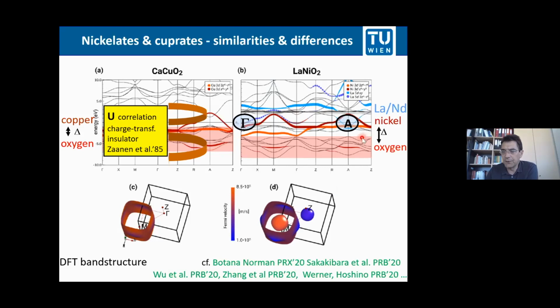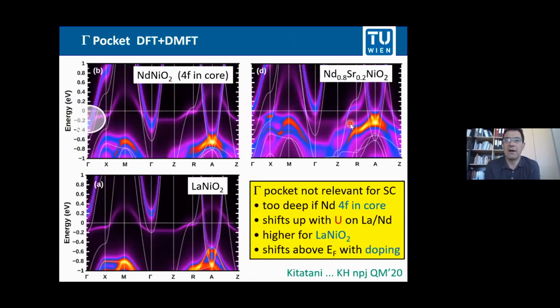Now, you have these 2 pockets, and then you also see here the z squared orbital. That is much closer to the Fermi energy than in the case of the cuprates. So that also has to be taken into account. But this is just a DFT calculation. Many people have done that. Now electronic correlations have to be taken into account. And what I will show you is that you can, in the superconducting doping regime, forget about the gamma pocket, the z squared orbital. The oxygen is anyhow not important, but the A pocket stays there, but it's only a passive bystander. Let's now go through all of these orbitals step by step in proper correlated DMFT calculations.